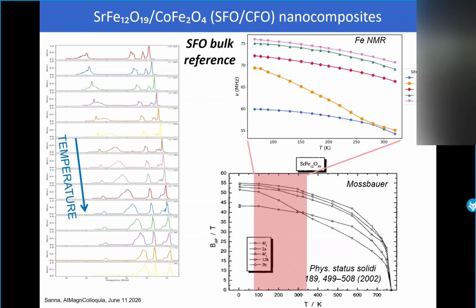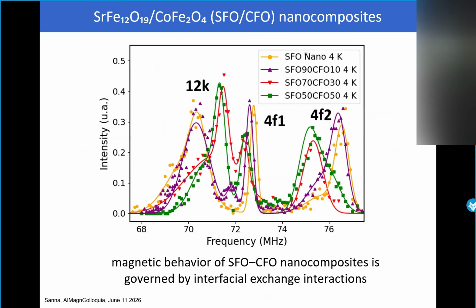We can measure this as a function of temperature, and we see here the behavior of the frequency as a function of temperature for each of these peaks. This is in very good agreement with the same behavior observed also by Mössbauer a few years ago, if we compare the same range of temperature. And so everything is very consistent. And now we are going to compare the spectra of different samples where we are increasing the content of the CFO.